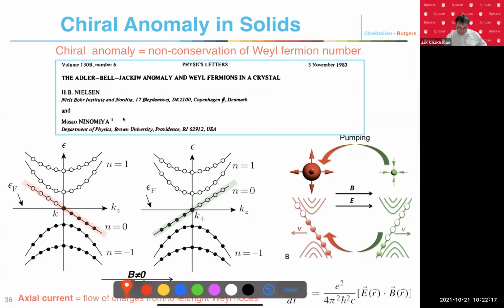And it's called the axial current. And there's this very new kind of electrodynamics called axial electrodynamics. And what's most important is this current is proportional to the electric field dot, not cross, but dot magnetic field. So in other words, it's a cosine between those two. And it's really the largest when they are parallel.